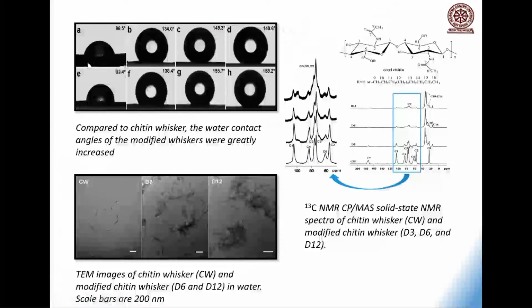Look at this, this is neat nanochitin. The contact angle is 86.5. As you put a large number of alkyl groups on the surface of nanochitin, you will see that nanochitin becomes increasingly hydrophobic. At a certain point of chemistry, you get super hydrophobic surfaces with a contact angle of 158.2.